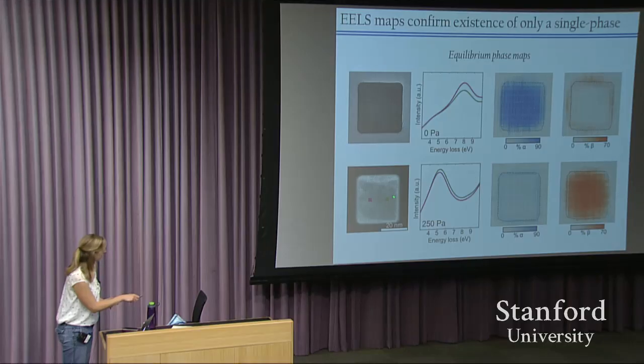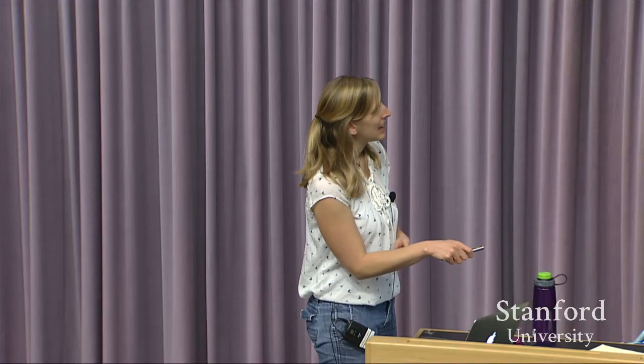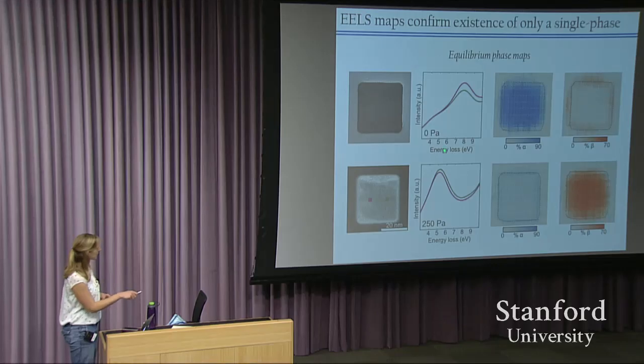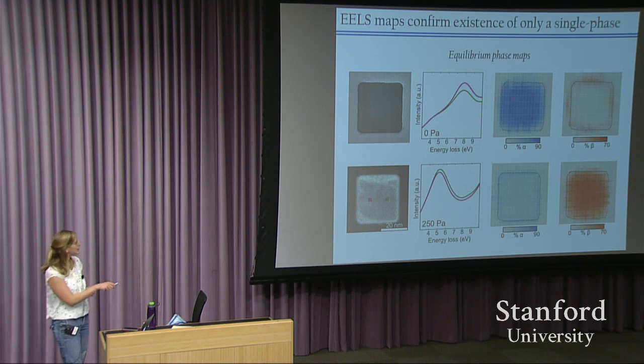at different points. So for example, if we take an EELS spectrum focusing the beam down to this point here shown in green at 0 pascals, we just have the alpha phase, and over here in pink, we also just have the alpha phase. And then if we increase the hydrogen pressure, in this case for pure palladium, to 250 pascals, at each of these points you'll notice they both exist in the beta phase. And what we can do is basically not just look at 2 points, but look at hundreds of points within the nanoparticle to figure out what phase it's in.